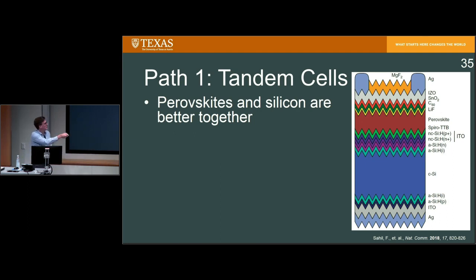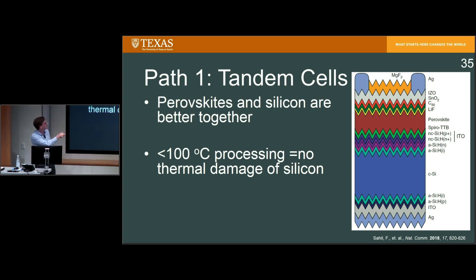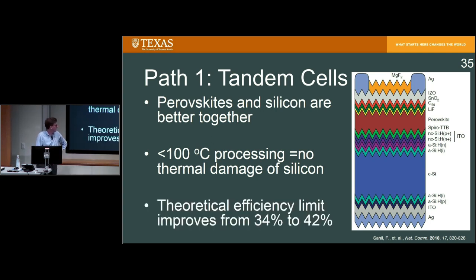But if you pair two materials in a tandem architecture like this, with different absorbing properties, you can raise this fundamental thermodynamic limit to a higher value and potentially get more bang for your buck and some cost reductions as well. The fact that perovskite can be deposited at less than 100 degrees C means that you can do what we call a monolithic integration. So you can double the amount of solar cell you have without doubling things like the interconnects or the balance of system costs, the sort of soft costs associated with hooking these things up electrically that you would normally have. And indeed, this is the actual quantitative efficiency jump that you can get from 34% up to 42% with a silicon perovskite tandem. And so 30% modules in such an architecture is not necessarily something that's unrealistic.